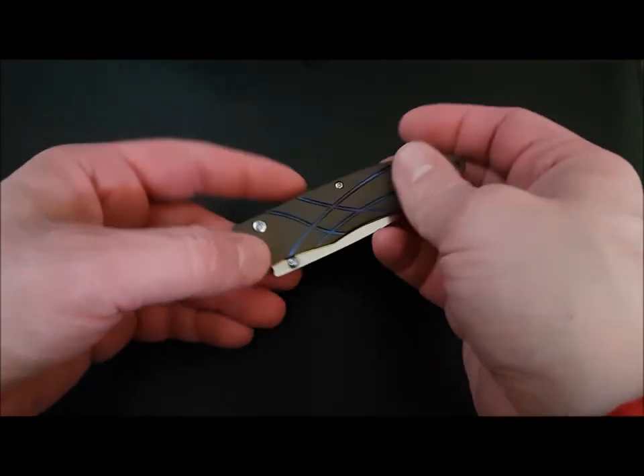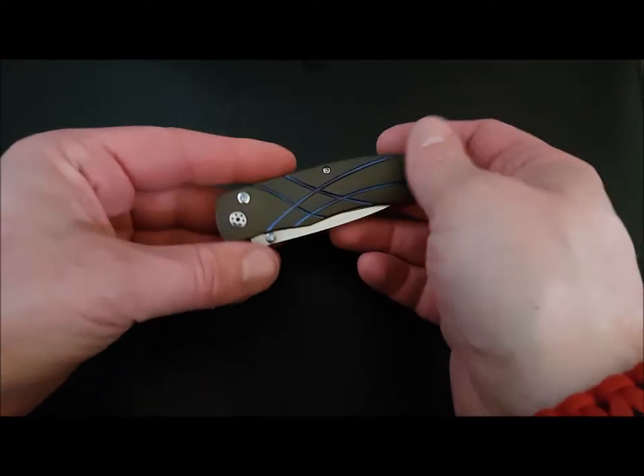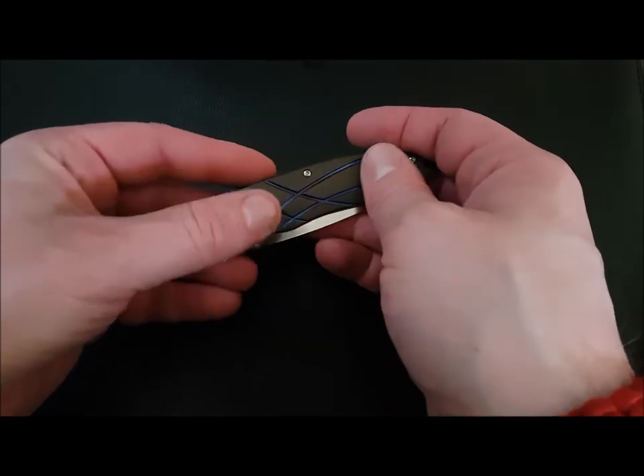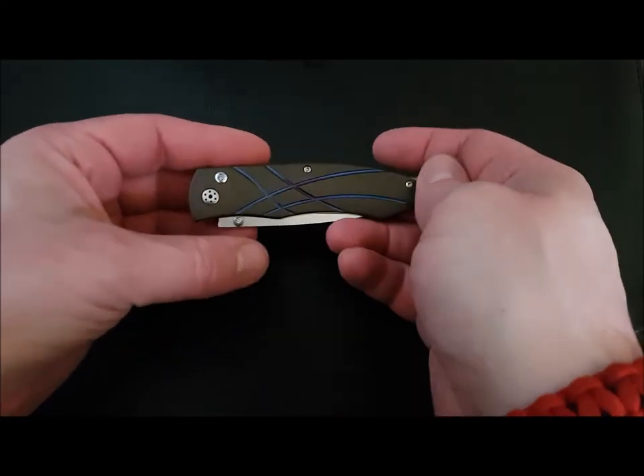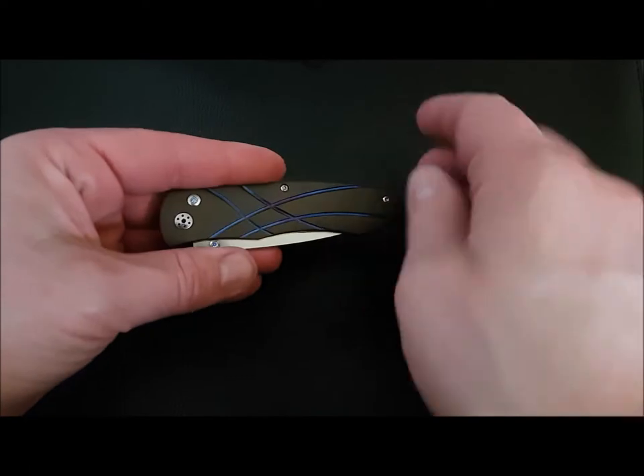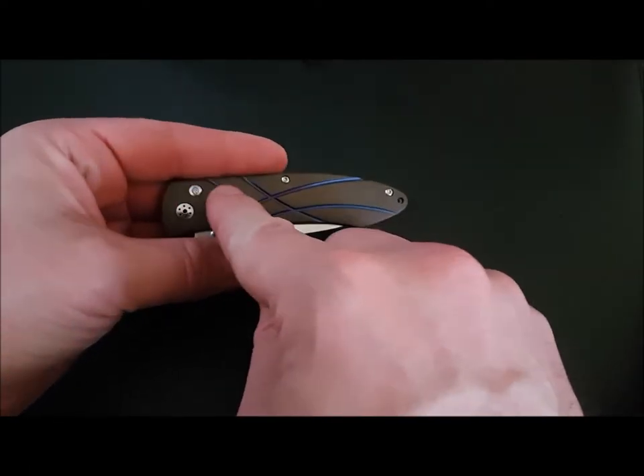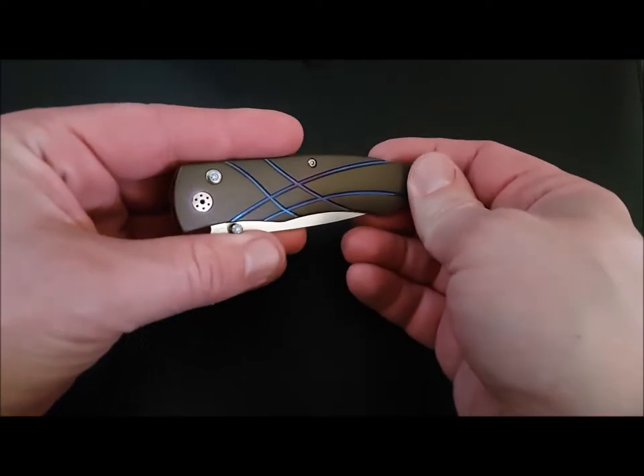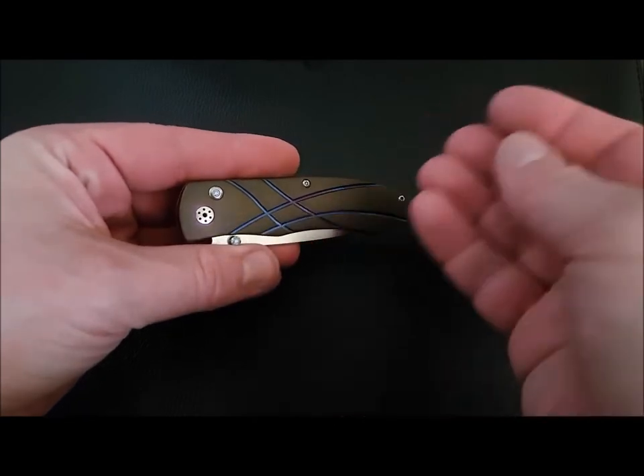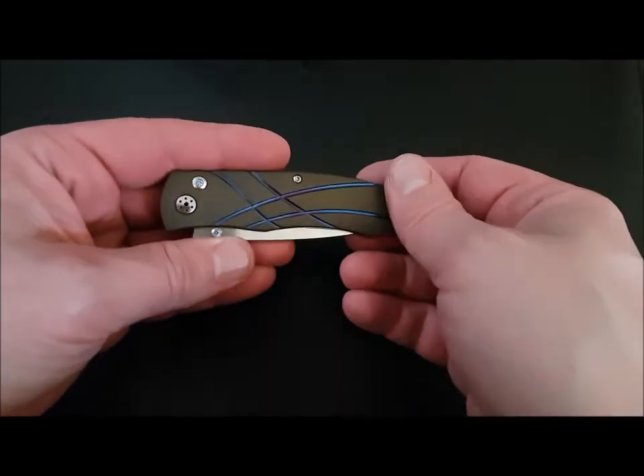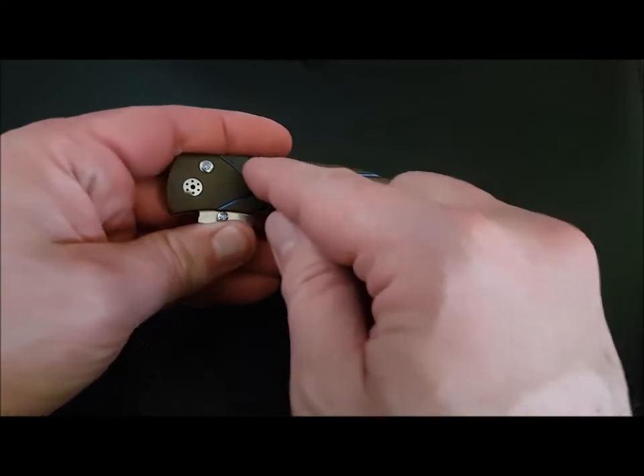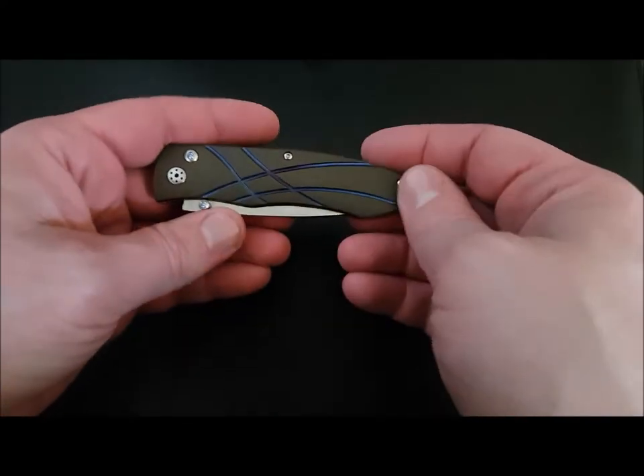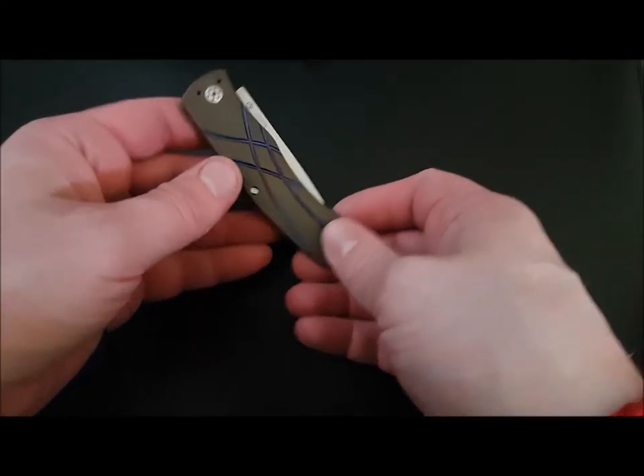So I started by polishing the handles up, seeing how deep the scratches went. Once I did a first pass with the polish, I then sanded any of the deeper scratches out and then re-polished. So prepared the handles. Then what I did was I had to go in and sand out the milled lines. You have to prepare the milled lines for anodization by making sure that you remove the original color and you make sure that the metal is all consistent and ready to go.